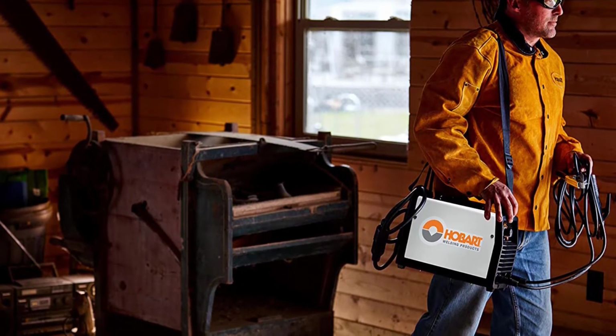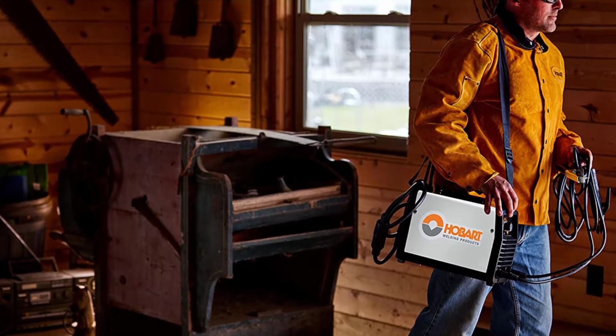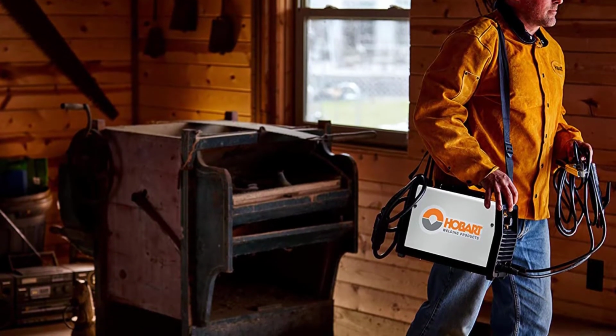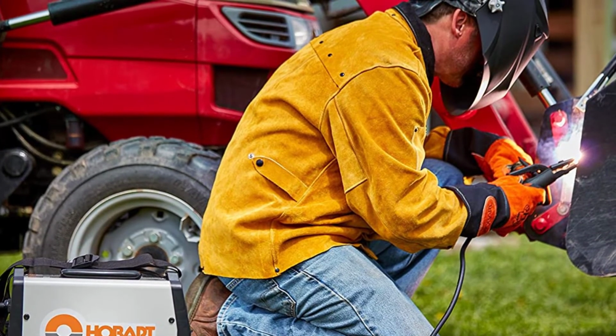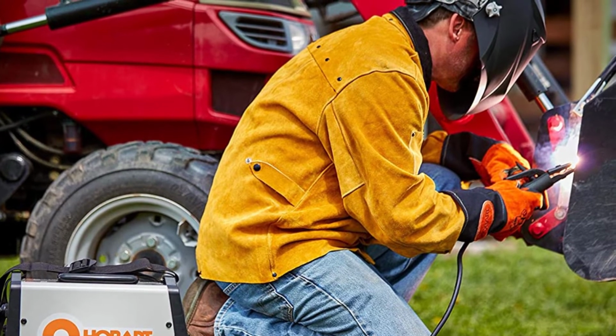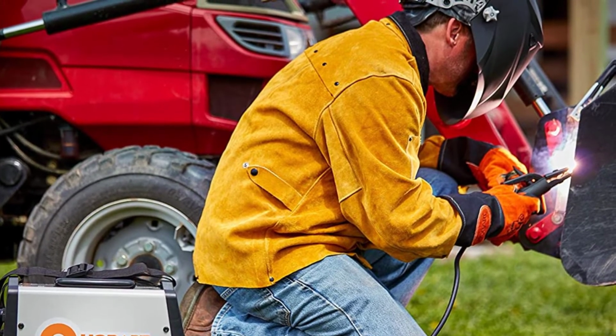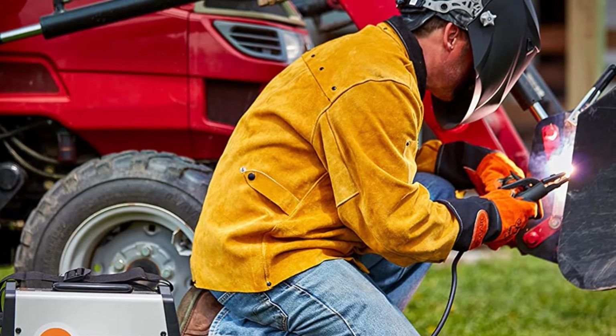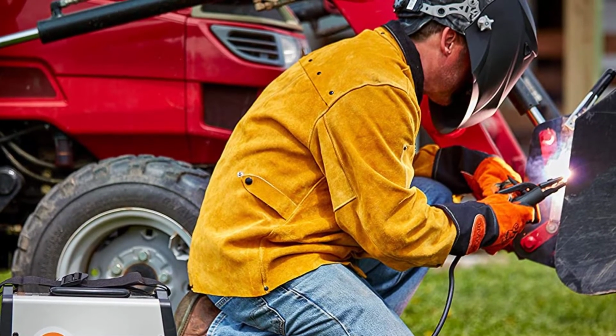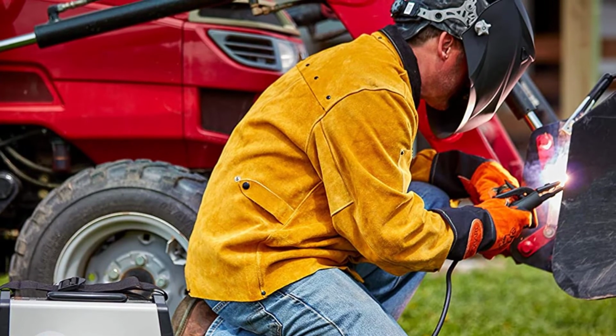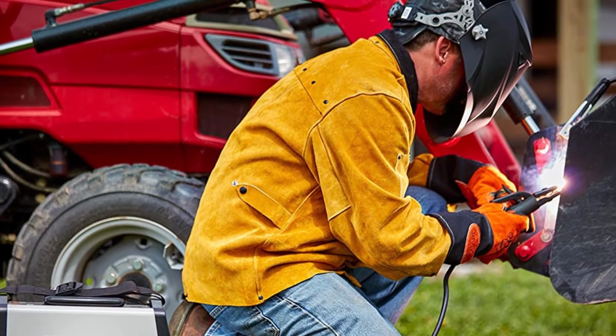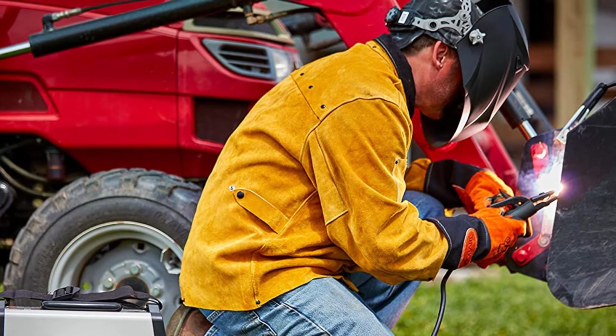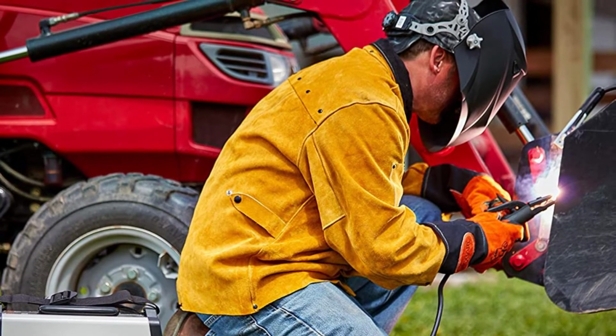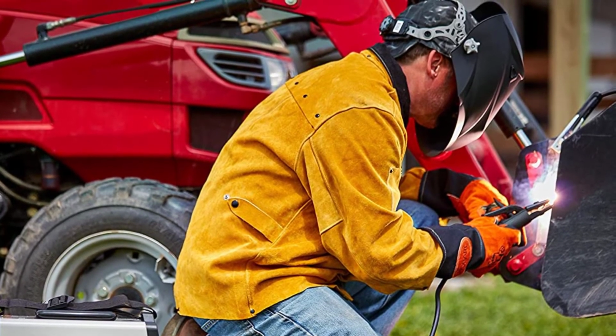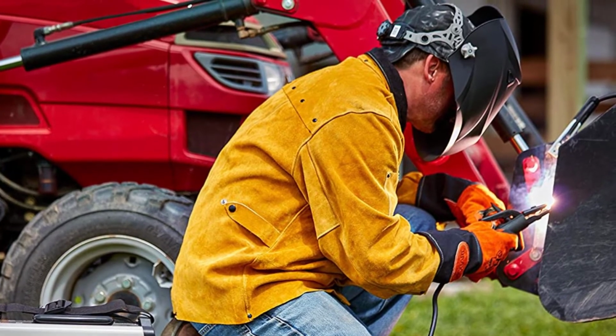I can't easily find fault with HOBART quality, and this is clearly evident in the high-quality electrode holder, ground clamp, and cables. It comes in at a very reasonable weight of 15 pounds. This is certainly a very handy portable stick welder with a good handle on the shoulder strap. I think it goes without saying that most people expect the very best from HOBART. This is why we pay top dollar for their welders. Ironically, this usually results in lower customer ratings on sites like Amazon. People expect more from high-end expensive brands and are, therefore, more critical. I believe this is, in true HOBART style, a very well-made machine, though I can't help being a little disappointed in the short duty cycle.